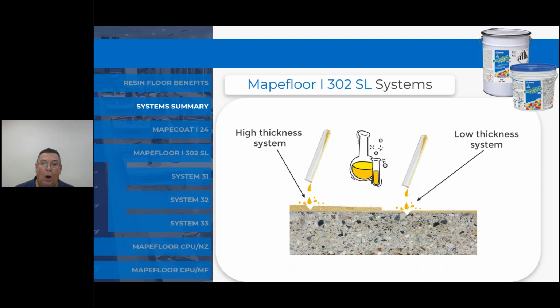The actual thickness of the floor has a direct relationship to, I guess, its robustness and ability to hold out chemicals and damage to the floor, still protecting the subfloor. The higher the thickness of the system, the better it can protect, and some surface damage still doesn't allow any chemicals or anything to get through the floor and to start to undermine that flooring system. With a low thickness system, a thin roll coat, if mechanically damaged, can provide access for chemicals to get straight through into the subfloor, and apart from deteriorating the concrete, can rapidly reduce the life expectancy of the coating.